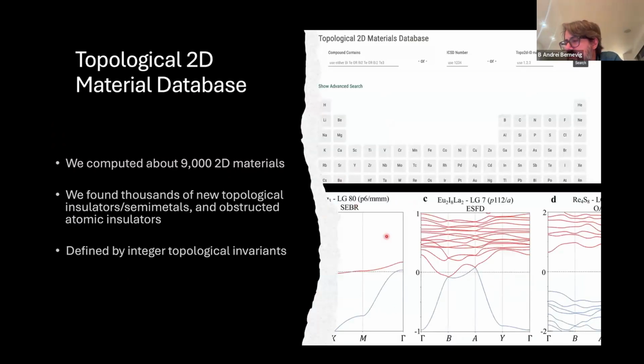Okay, to close, I've presented three systems: twisted bilayer graphene, molybdenum ditelluride, and rhombohedral graphene, for which there are results. People have twisted them. In one of them, they see heavy fermions, Mott-Hubbard bands, Mott semimetal, and in the other, fractional Chern insulators. But if you look at the number of materials that admit two-dimensional single layers, there are about 9,000 computed. This is from Nicola Marzari's database, but you can also get them at our database, where you compute the topological index. We took Marzari's database and computed the topological invariants for these single layers.